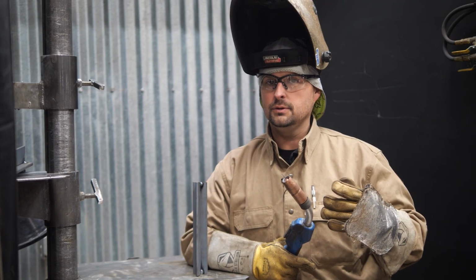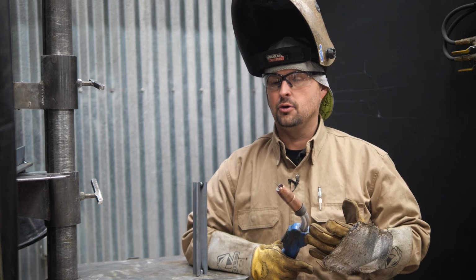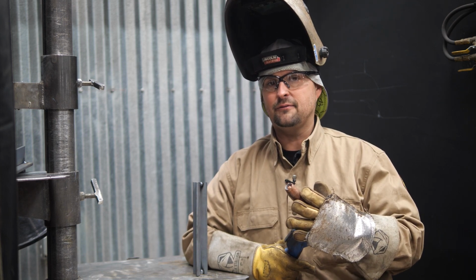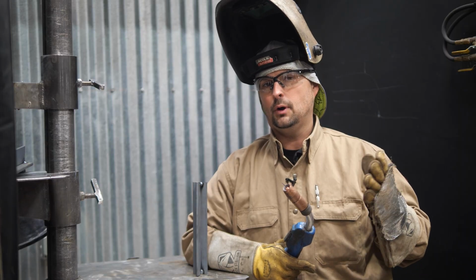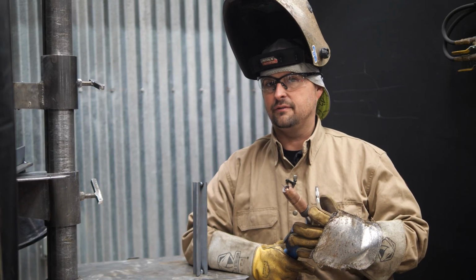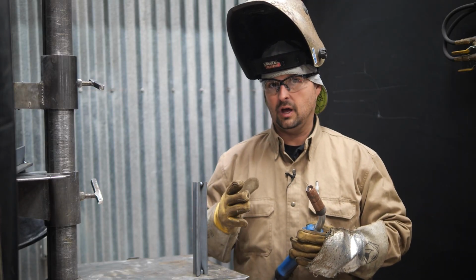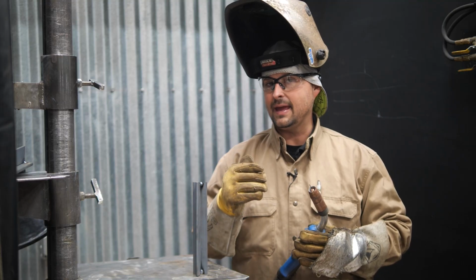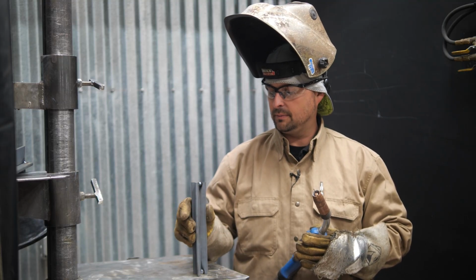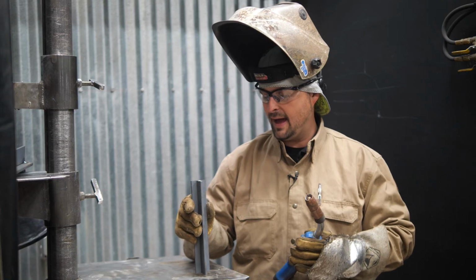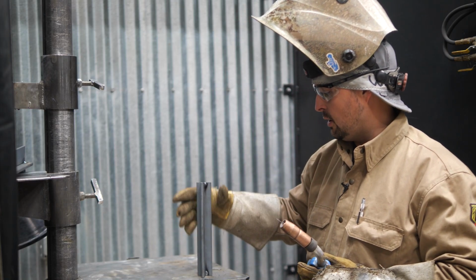All right, I'm starting off with the 777, the Hobart product, running 415 inches per minute and 26 volts. And we're in DC electrode positive. I am running a 75-25 argon CO2. I'm going to run about 45 CFH. And then I'm just going to run a vertical up here, take a look at what the amp and volt values are when I'm done, because my machine's going to be able to record that. Here we go.